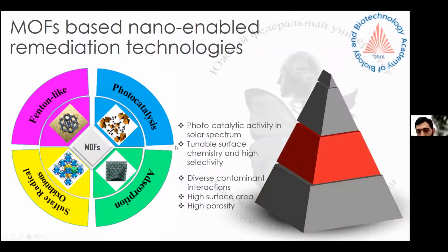The next level of this pyramid is the photocatalytic activity of this metal-organic framework. Because they have a narrow band gap, they can easily be activated during solar light irradiation. So this is very advantageous during photocatalysis or photo-Fenton-like reactions, where we can activate them by sunlight. And also they offer tunable surface chemistry, where we can add other guests inside the structure and make this band gap become narrower and more active.